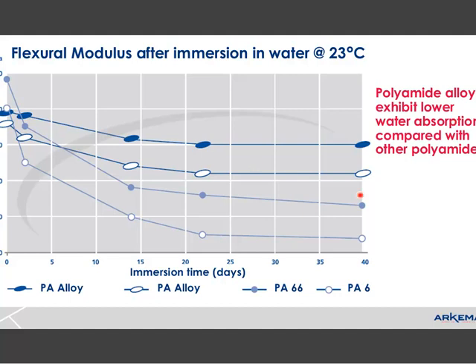And one other slide I'll present on these polyamide polyolefin alloys is related to moisture absorption, and in this case it's expressed as flexural modulus and its change from water exposure. With these first two materials, what we see is that after exposure in water for 40 days, you have some reduction in flexural modulus, but it's relatively low. Whereas compared to other polyamide products, which have much higher moisture absorption, you're going to have a much more significant drop in flexural modulus properties.